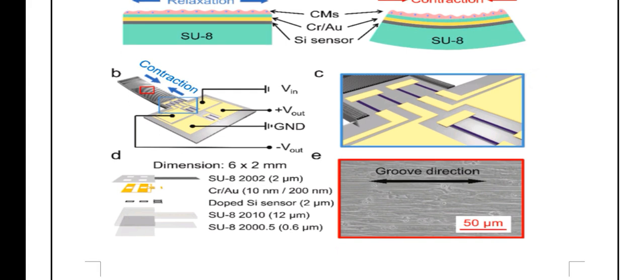In figure 1d, there is a layered structure of the cantilever. The cantilever is composed of multiple layers for optimal performance. First of all, there is the SU8 layer, which ensures flexibility and biocompatibility with cardiomyocyte culture, and the chromium and aurum, means gold, layer provides electrical connectivity, and the silicon sensor layer detects deformations caused by the contractions. The dimension of the cantilever can be 6 mm multiplied by 2 mm, designed to maximize the displacement for force measurements.